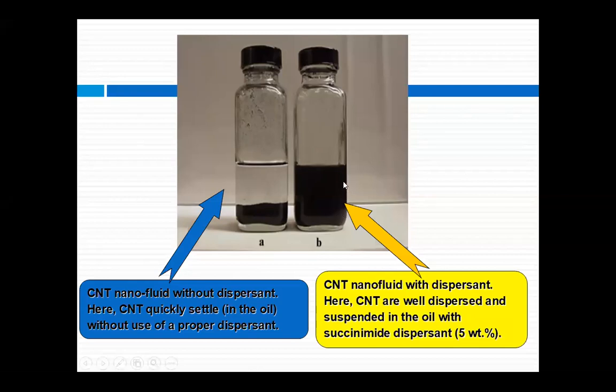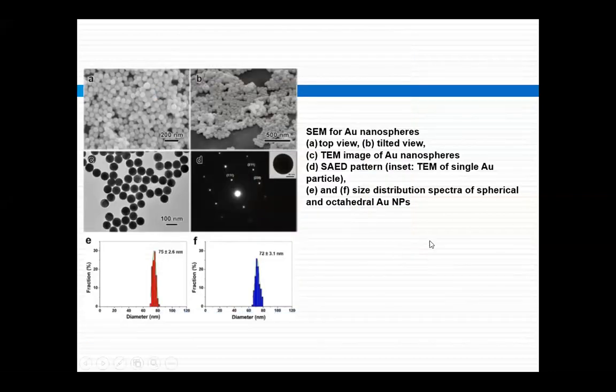So on the right side surfactant is added, but how much quantity? In the case of nanofluid or ferrofluid, up to around 5% nanoparticles are suspended in the solvent. But the amount of surfactant is more than the nanoparticles to make a stable suspension solution. So now you can see that you can have the stable suspension solution for a longer duration, in days, not only in hours. That is the important thing.